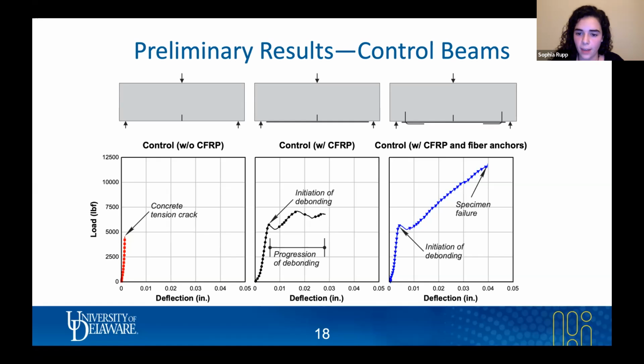And this is due to the fact that the CFRP starts to debond, and then the stresses from the CFRP start to transfer to the anchors and into the concrete. And the beam will continue to take load until most likely the anchors fail by anchor pullout, which is when the anchor pulls out of its hole, or the CFRP will rupture around the anchor hole.